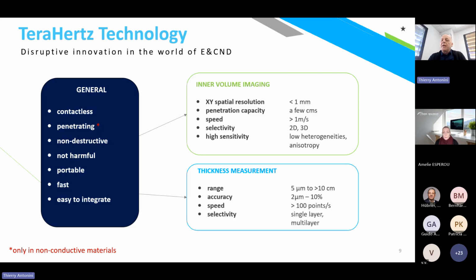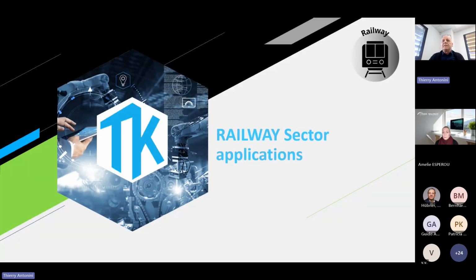And for thickness measurement, we can measure from 5 microns, so a very small layer, to a larger layer up to 10 centimeters with quite good accuracy, plus or minus 2 microns for very small thickness, and 10% of the measurement for higher thickness. Speed, more than 100 points of measurement per second, quite adapted to industrial production speed. And a very important point is the possibility to discriminate layers in a stack of multi-material coating, for instance.